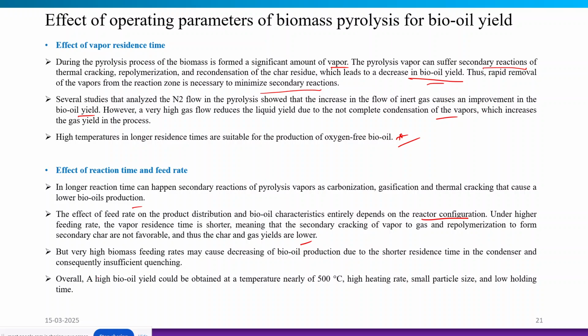So we can say that through the research we have found out that a high bio-oil yield could be obtained in the temperature range of 500 with a higher heating rate, a smaller particle size, and low holding time.